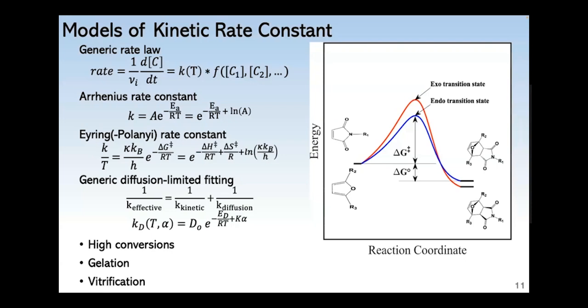And in fact, a better model, which you can use to directly relate with the reaction thermodynamics, is the Eyring-Polanyi rate constant, which is instead described by a Gibbs energy of activation, or the delta G double dagger. The enthalpy of activation is analogous to the activation energy, and the entropy of activation is analogous to the frequency factor. And then the Eyring rate constant also has a built-in temperature term and the Boltzmann and Planck's constants in it.